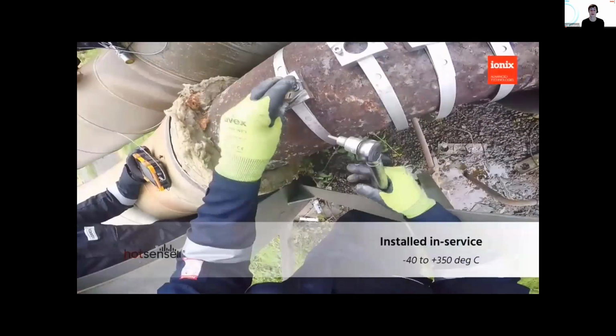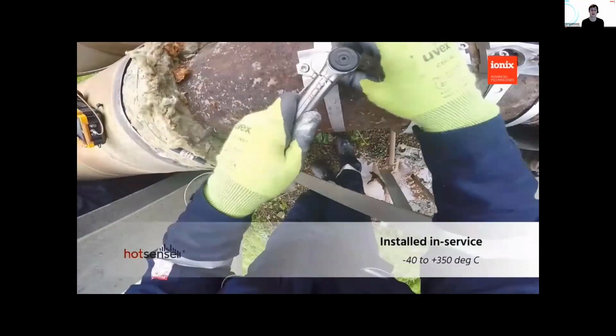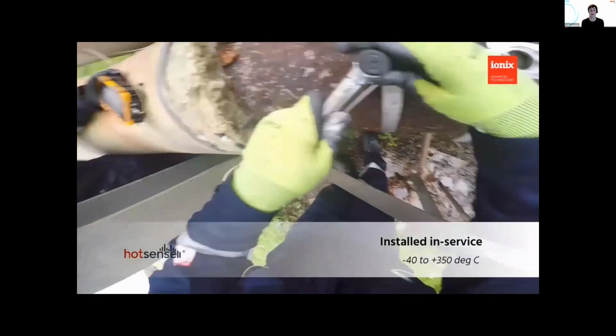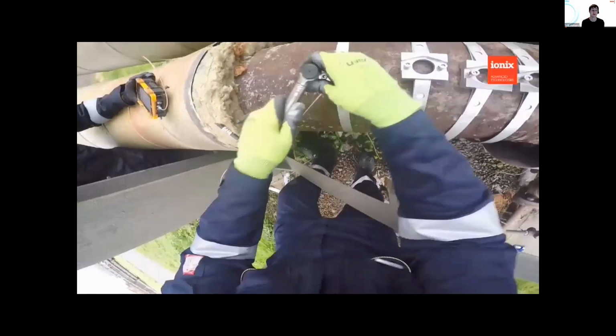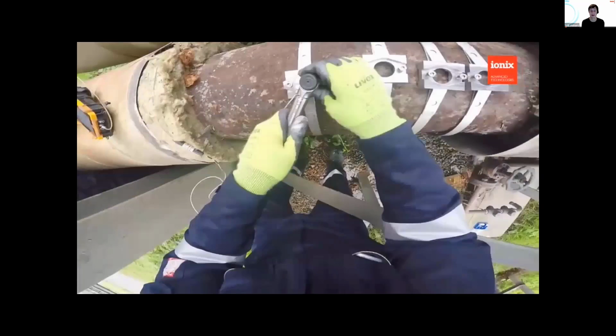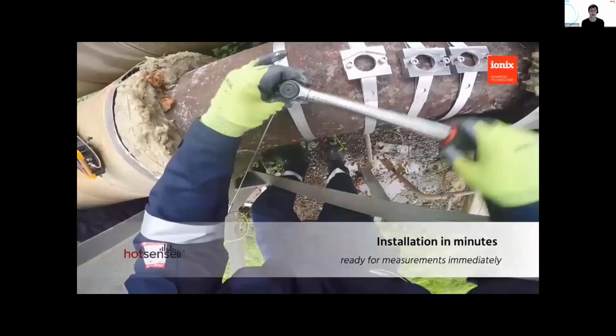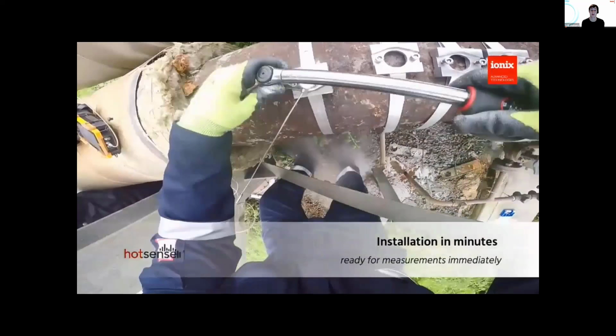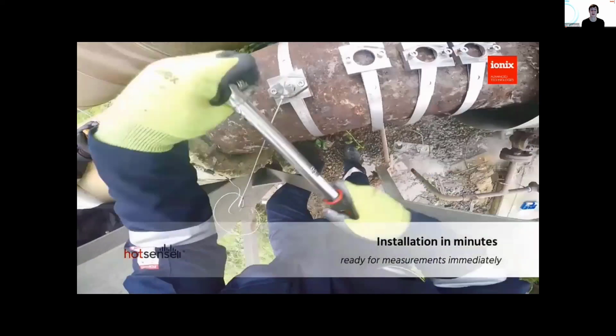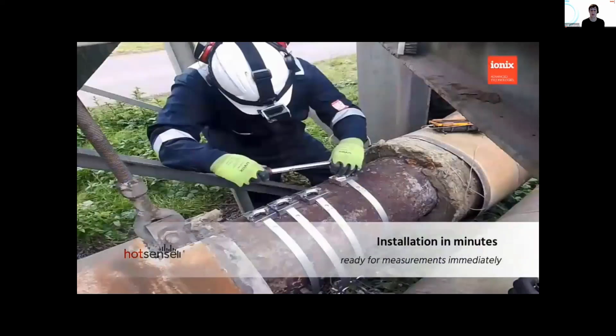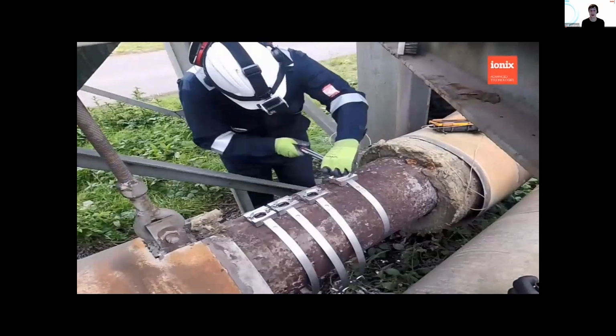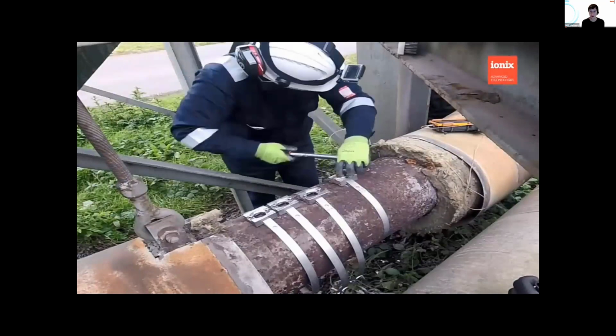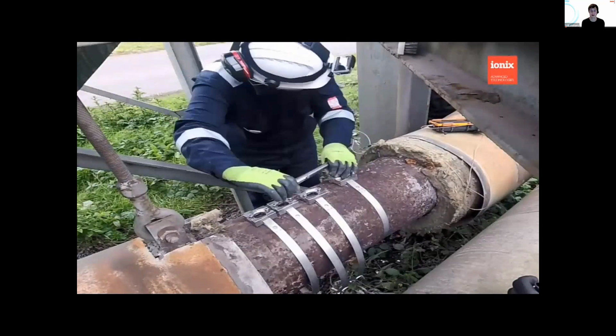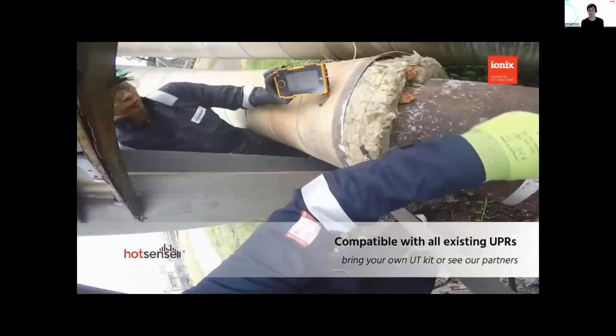and it's the same tool, the same hex key, for the straps as the transducers. The transducer with the foil is dropped in, initially hand tightened, and then we connect this just to a standard thickness gauge or flaw detector, because it works like a standard UT transducer, and then we're just tightening it up on each of the bolts to a set torque. The coupling that you get from this is stable for many years, even if the pipe is heating and cooling.